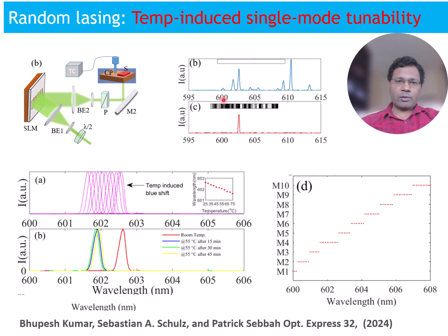Before going forward with continuous tunability, we first confirm the spectral stability at higher temperature. We performed measurements at a higher temperature at different time intervals and found that for up to 45 minutes the spectrum remains stable within plus minus 0.1 nanometer. Now we move to continuous broadband tunability.